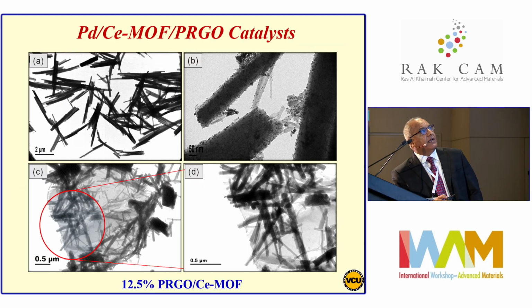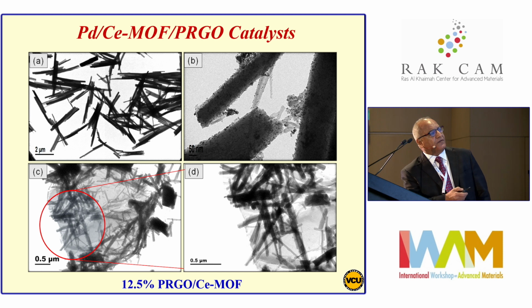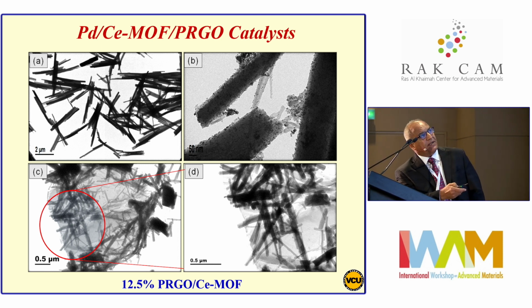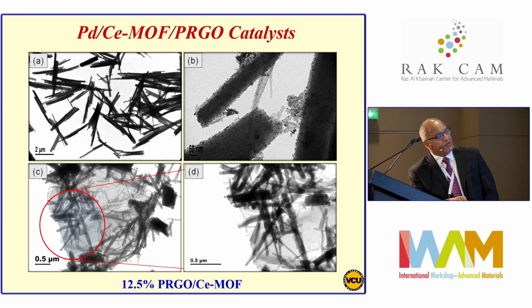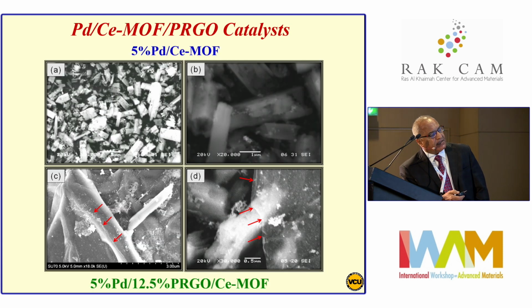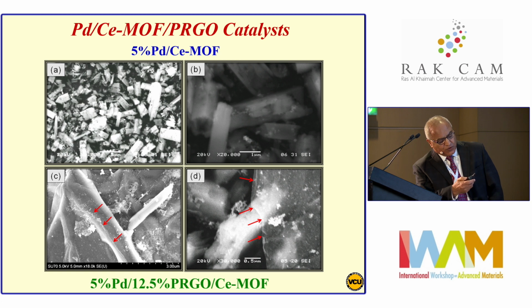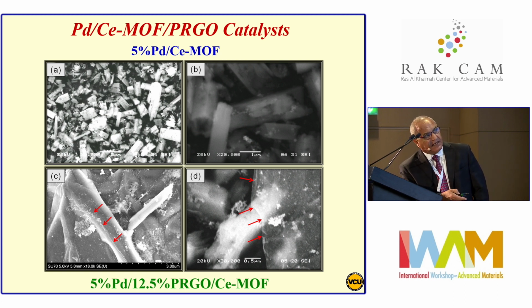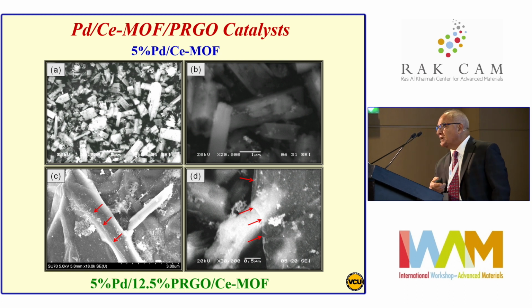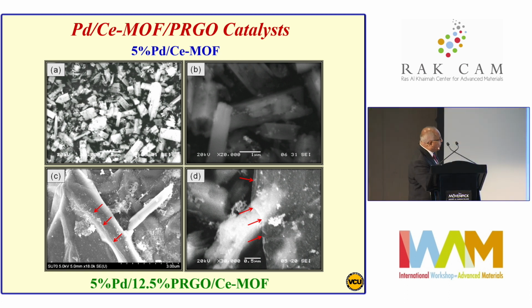Now we go to the reaction, and before this is the SEM of the catalyst. This is within the cerium-MOF here, and here within the hybrid structure. So the first one is just the palladium on the cerium-MOF, and this is palladium within the hybrid structure. You can see the hybrid structure better in this next TEM image, where you can see layers of reduced graphene oxide in addition to the cerium-MOF crystals. So the idea of having a hybrid structure, based on the characterizations that we have, appears to be working here.